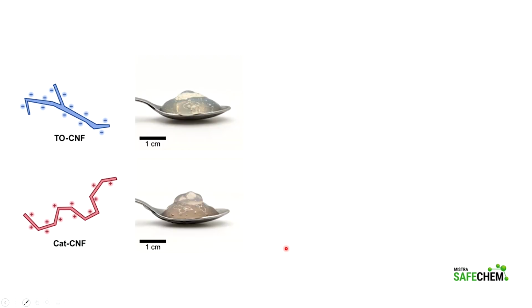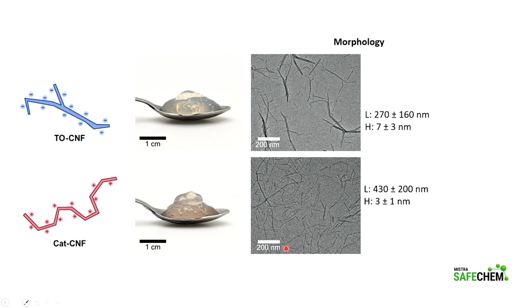If we look more into detail about these materials, then we can see first that since they are so long, they form gels. And what is interesting to see here is that in the upper part, we don't see any part of the dye that we had before. In the lower one, we can see a little haze, but still it's a very clean and pure material. If we look more into detail into its morphology, you can actually see these nanoparticles in the nanoscale. And we can see that depending on the route that we use to extract them, they have different morphologies.